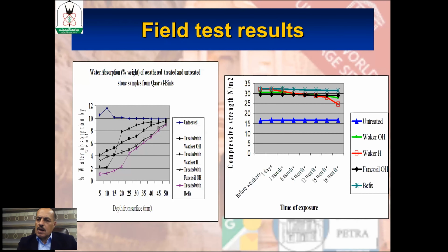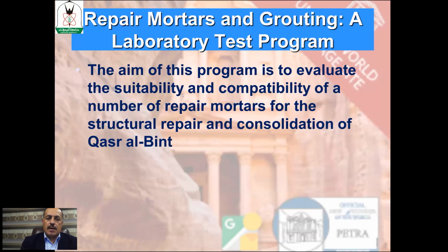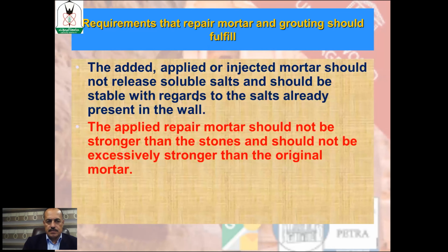This field testing program took us a period of 18 months, where at different intervals, readings were taken and samples were taken and analyzed in the laboratory for the different properties that I mentioned. In addition to the stone consolidant testing program, we also conducted a repair mortars and grouting testing program, laboratory and field again. And the aim was to evaluate the suitability and compatibility of a number of repair mortars for the structural repair and consolidation of Qasr al-Bint.